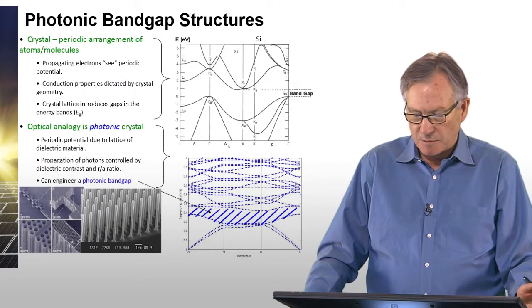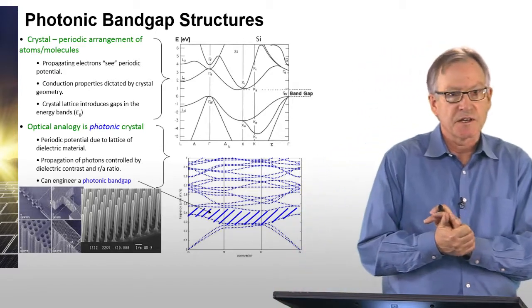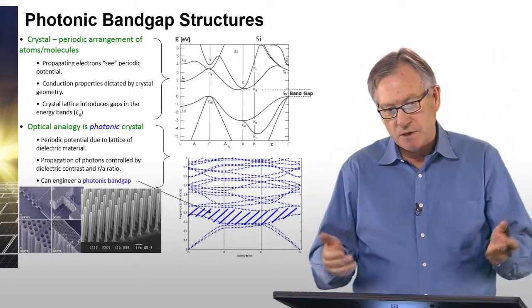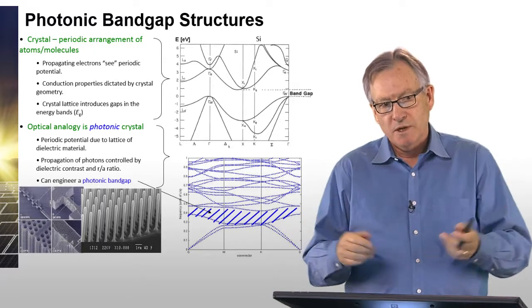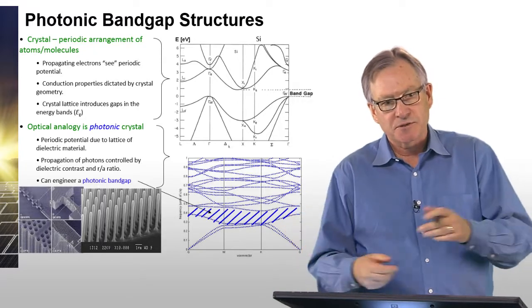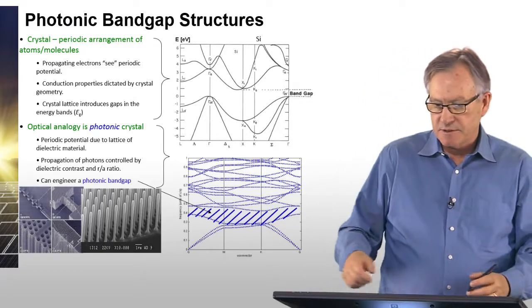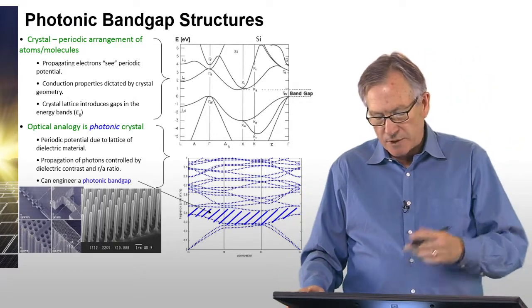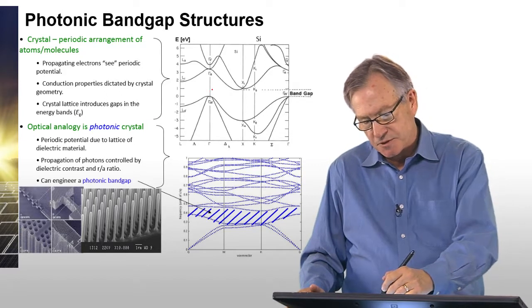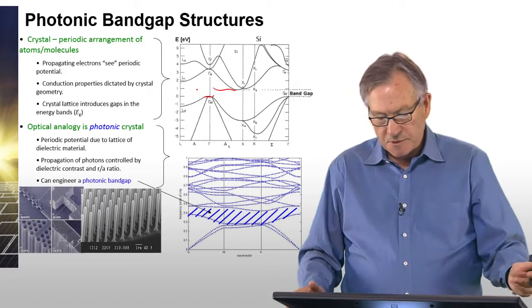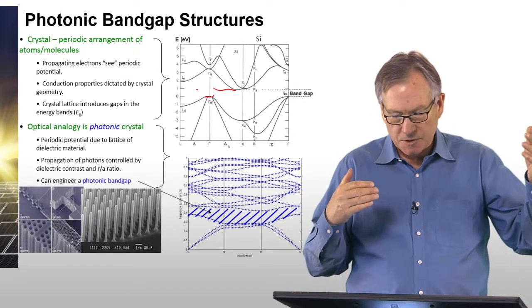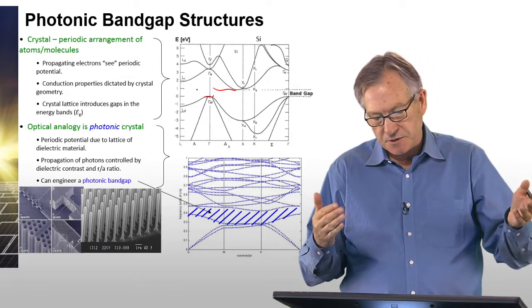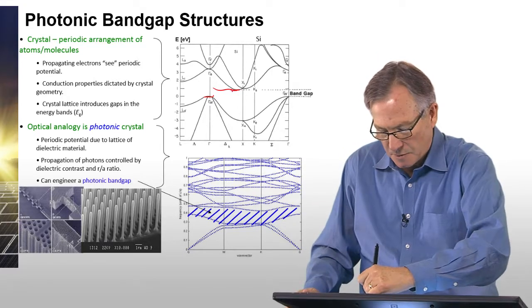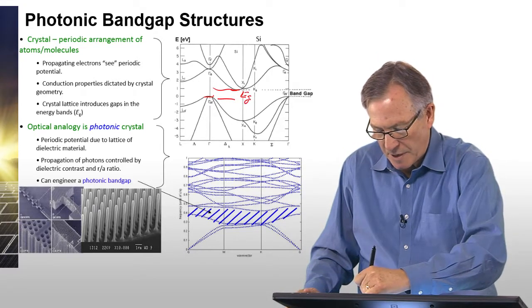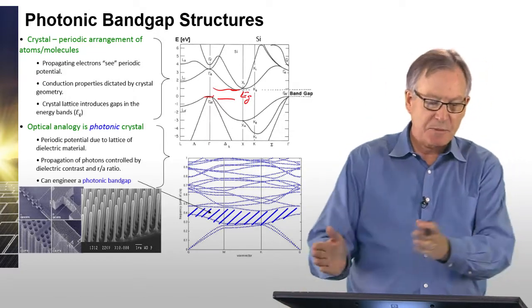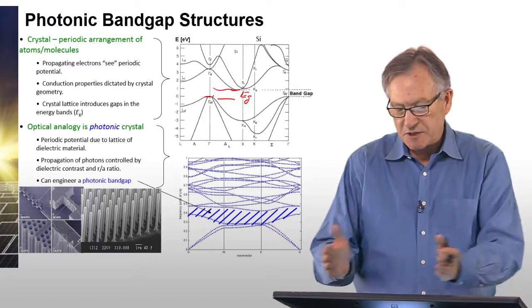Photonic band gap structure materials, I don't want to go too much into detail of this other than to say that if you make a periodic array of scatterers optically, it plays the same role as a periodic array of atoms does in creating a band structure and creating a band gap. That is, in terms of the wavelength or momentum of electrons, gaps are opened up in the spectrum of a crystal in terms of its electronic states that lead to the formation of a band gap. And so this difference between here and here is what we call the band gap of the semiconductor. This is a different kind of picture than I showed before. This is a picture in momentum space of the band gap.